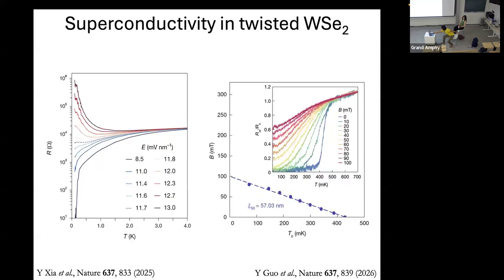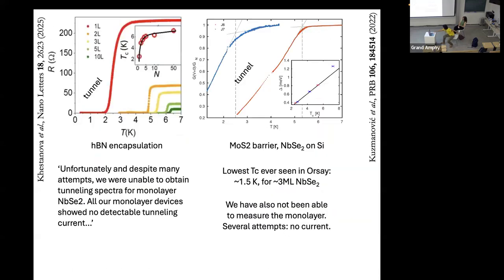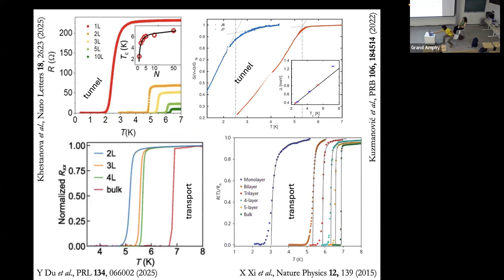So just to correct something I said, this is correct. They were able to measure transport on the monolayer, no problem. They were never able to get tunneling data. And since we now know this is the correct figure, you can see two-layer here, it's less than 5. Two-layer here, it's about 5. I mean, everything is lower. Even the bulk is lower.